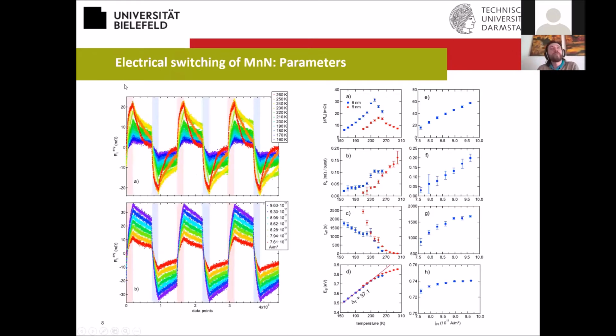Okay, so now let's have a look at the temperature dependence and the current density dependence of the switching of this manganese nitride. First, let's have a look at the temperature dependence. So this is the left column where we extract the parameters I've just talked about. You immediately see that with increasing temperature, the amplitude of the switching goes up. And we see some difference between 6 and 9 nanometers. So for 9 nanometers, this amplitude is smaller and the peak is at higher temperature. Then the switching efficiency, which is the initial slope of the switching, is higher for the 9 nanometers film at higher temperature. But you see this nice shift of these curves. So for thicker films, you get the same efficiency only at higher temperatures.